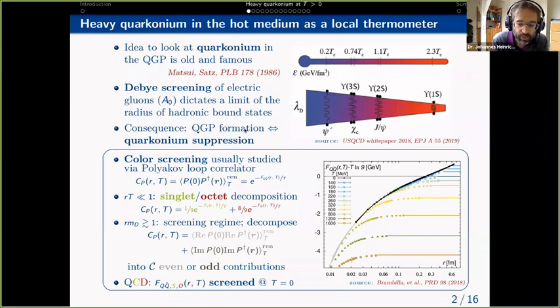This idea is pretty old. It was first brought up by Matsui and Satz about 35 years ago, now with more than 3,000 citations. The idea was to take a potential model to describe charmonium. If you have Debye screening, there will be a screening radius, and if that screening radius gets smaller than the radius of the state in your potential model, the state should not exist anymore and should be dissolved. Therefore you would see charmonium modification or suppression as intertwined with QGP formation.